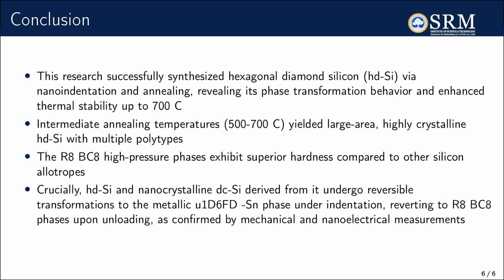This research successfully synthesized hexagonal diamond silicon (HDSi) via nano-indentation and annealing, revealing its phase transformation behavior and enhanced thermal stability up to 700 °C. Intermediate annealing temperatures (500-700 °C) yielded large area, highly crystalline HDSi with multiple polytypes. The R8/BC8 high pressure phases exhibit superior hardness compared to other silicon allotropes.